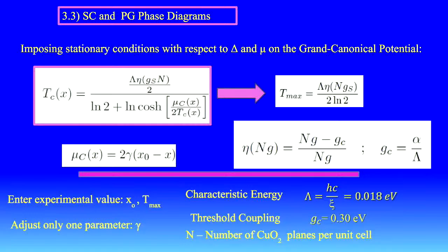The dome appears here because you see that when this mu is zero, the hyperbolic cosine is one and the logarithm is zero. So we have this value for the T maximum in terms of that GS and then the number of planes.